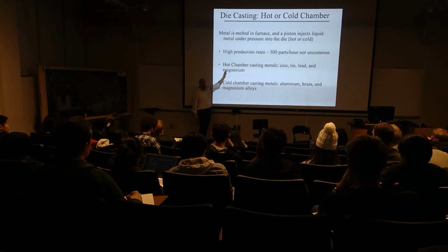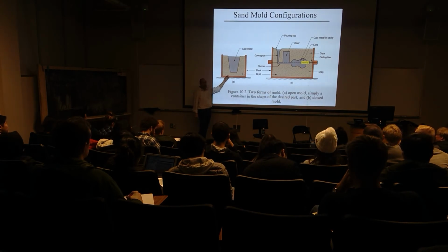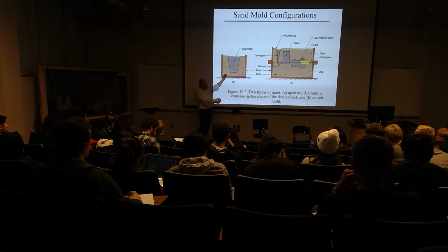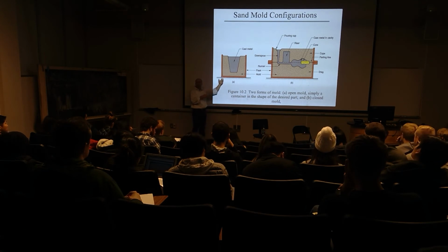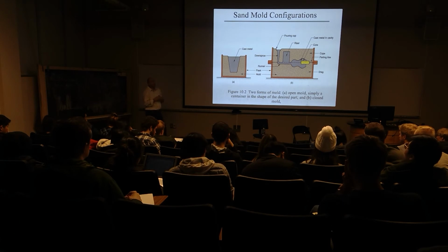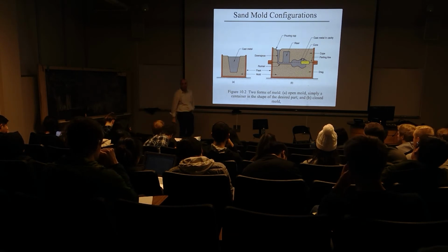develop parts from. So if I go back to this process, we can almost cast any metal because the melting temperature of this material, non-metal, is much, much greater than that of any metal. So the metals we're looking at might have melting temperatures in the range of up to about 3,000 degrees Fahrenheit, maximum. You know, and the steel is just going to be around 2,600 or so, and that's no problem to be able to cast within a sand assembly.